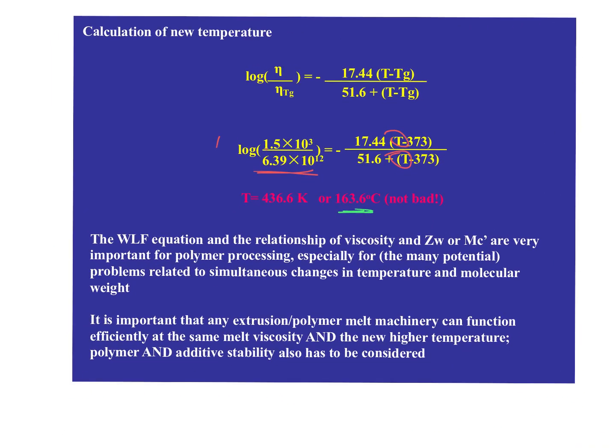So you just need to be familiar with the rules, how logs work. Okay, make sure everyone understands how logs work. And then you can solve for these things. So the WLF equation and the relation of viscosity and Z_w or M_c' are very important for polymer processing, especially for the many potential problems related to simultaneous changes in temperature and molecular weight. Okay.